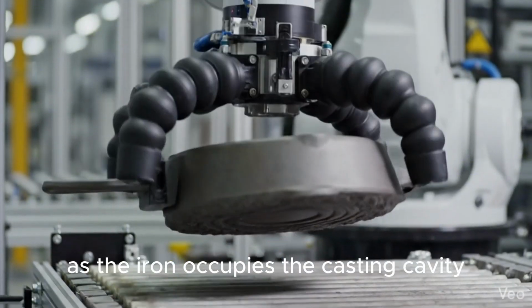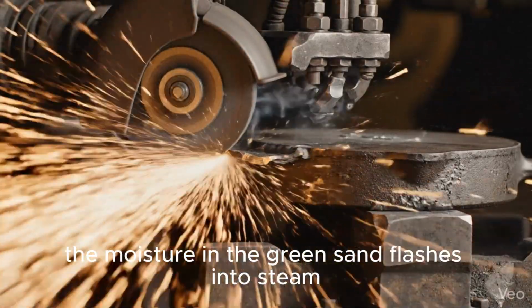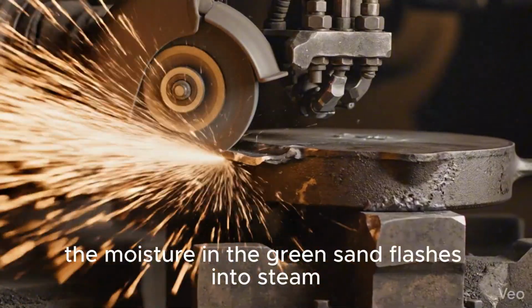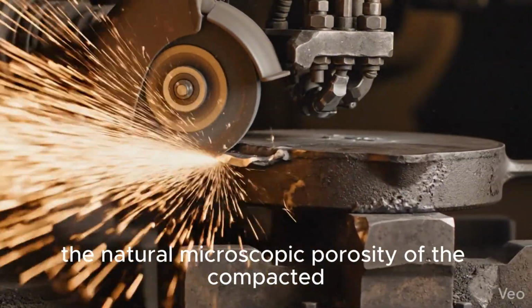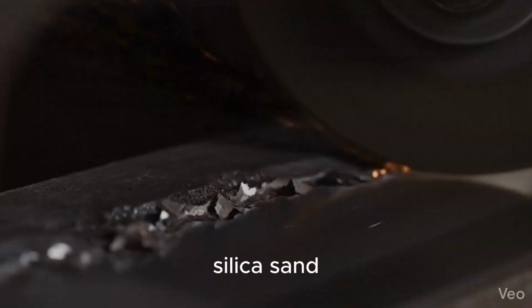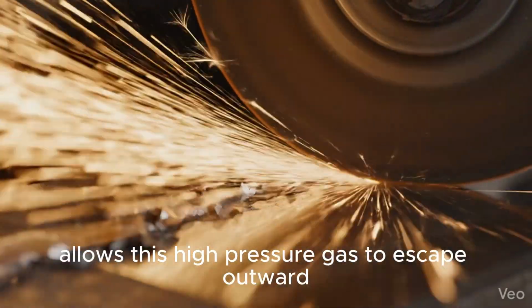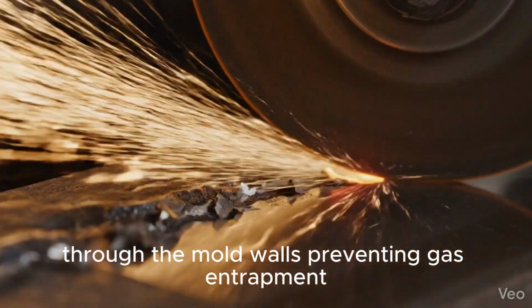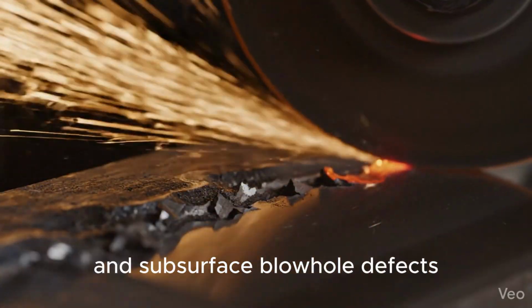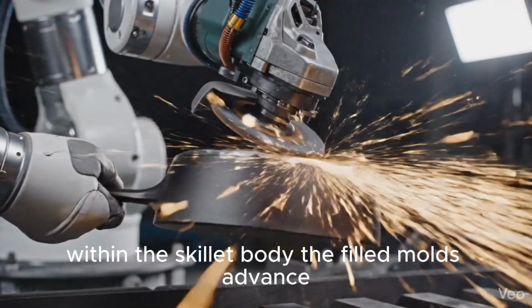As the iron occupies the casting cavity, the moisture in the green sand flashes into steam. The natural microscopic porosity of the compacted silica sand allows this high-pressure gas to escape outward through the mold walls, preventing gas entrapment and subsurface blowhole defects within the skillet body.